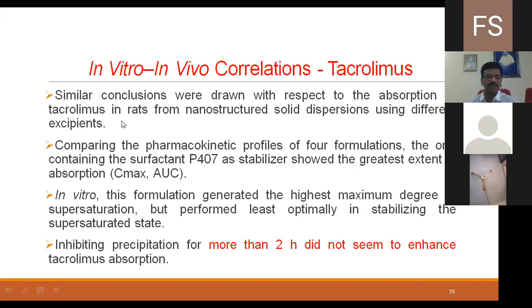Another example is tacrolimus. Similar conclusions were drawn with respect to the absorption of tacrolimus in rats from nanostructured solid dispersions using different excipients. When comparing the pharmacokinetic profiles of 4 formulations, the one containing the surfactant as a stabilizer showed the greatest extent of absorption. So that is what we wanted. That is the parachute effect that we wanted from the surfactant, and it was obtained from tacrolimus when tested with the surfactant P407. In vitro, this formulation generated the highest maximum degree of supersaturation, but performed least optimally in stabilizing the supersaturated state. So, inhibition of precipitation for more than 2 hours did not seem to enhance tacrolimus absorption. So, not required. We need not maintain the supersaturated condition of tacrolimus for more than 2 hours.